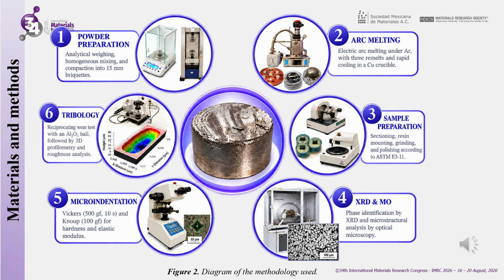In addition, tribological wear resistance was assessed using linear reciprocating wear tests, in which the samples were subjected to a load of 2 newtons at the frequency of 2 Hz for a period of 3,600 seconds on a 5 mm track, using a 5 mm diameter alumina ball as a sliding counter body. Once the test was completed, the coefficient of friction was determined and the wear marks were characterized using a three-dimensional profilometer, thereby enabling the volume of worn material to be quantified and the resulting surface topography to be analyzed in order to establish the specific wear rate.